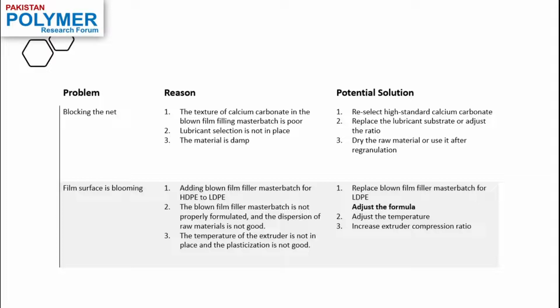Thirdly, it's really important to dry the raw material before using, and if the raw material isn't dry, you're either going to get the material stuck in the sieves, or you're going to get other issues in your blown film, such as the fisheye. Another problem that occurs is the blooming of the film surface. Well, the blooming means that the surface has some low concentration of the bulk material, like the plasticizer, and it occurs due to the high surface energy.